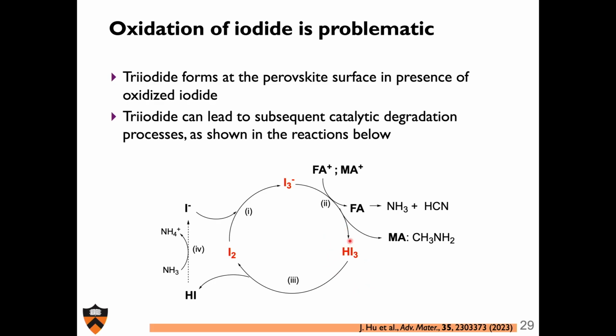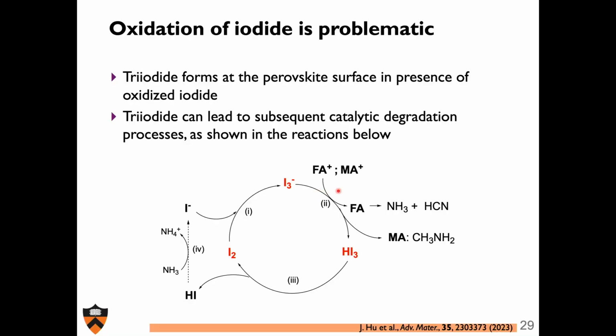And then I make HI3. This is not a very stable product. And so eventually I make HI and I2. And I2, in the presence of more iodide, I just make triiodide again. And so I have this unfortunate catalytic cycle. Only one has to happen, and it just keeps going. And if I do this in the presence of methylammonium, I will see lots of lead zero, and that's because of this amine, which is a reducing agent toward lead. And so you will see lead zero upon this catalytic reaction if you have methylammonium around.